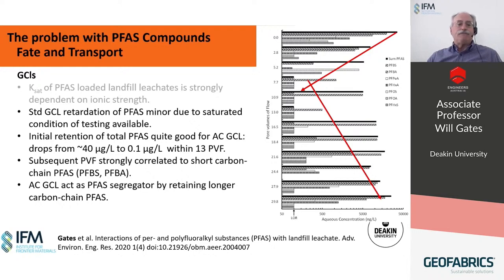So basically, while the activated carbon GCL works well for the larger or longer carbon chain length PFAS, such as PFOA and PFOS, it's likely not so effective for shorter carbon chain lengths over time. And so this is going to be important for understanding when we design future landfills.